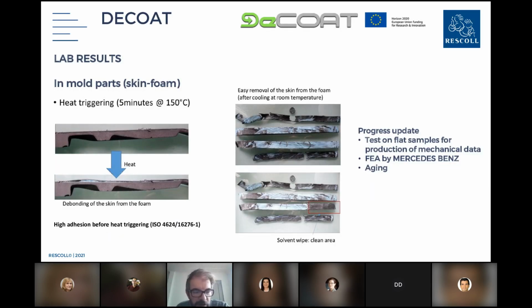For the Mercedes-Benz use case, we got cockpit parts directly manufactured with a primer thanks to Mercedes-Benz. They cut them in slices and then we tested the adhesion with ISO 4624, and it was quite nice regarding the reference material with no primer. And then we debonded the parts.